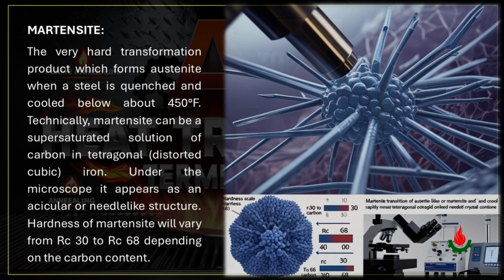Martensite. The very hard transformation product which forms from austenite when a steel is quenched and cooled below about 450 degrees Fahrenheit. Technically, martensite can be a supersaturated solution of carbon in tetragonal distorted cubic iron. Under the microscope, it appears as an acicular or needle-like structure. Hardness of martensite will vary from Rockwell C30 to Rockwell C68, depending on the carbon content.